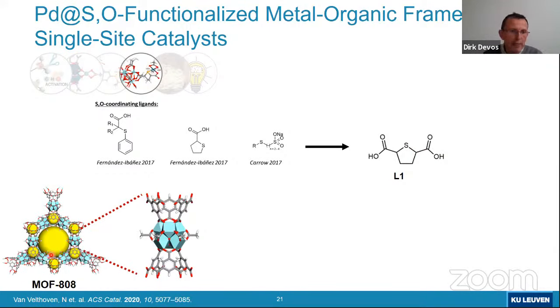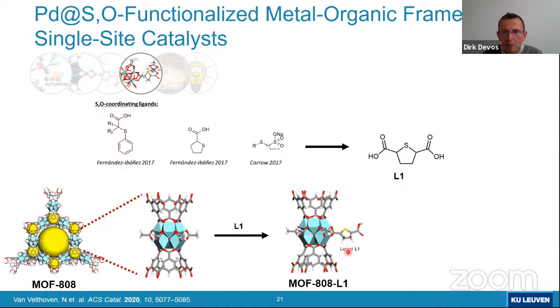So if indeed we zoom in again on this MOF-808 structure, we worked with this cluster and we replaced these acetic acid or these acetate linkers. We replaced this with this ligand, which we just termed L1. So actually one of the carboxylic acid groups is now just being docked on the zirconium cluster, while you still have the thioether and also a carboxylic acid free to coordinate the palladium.